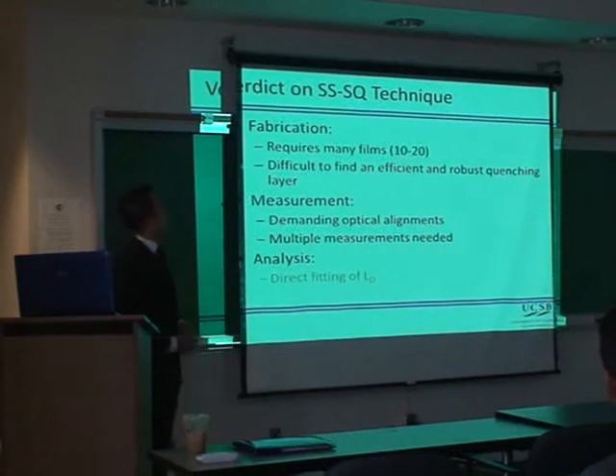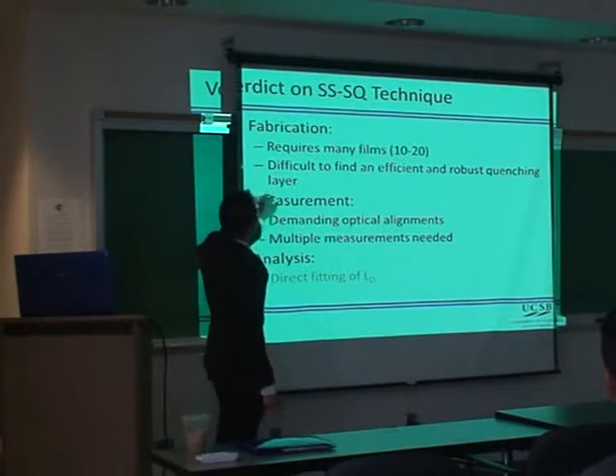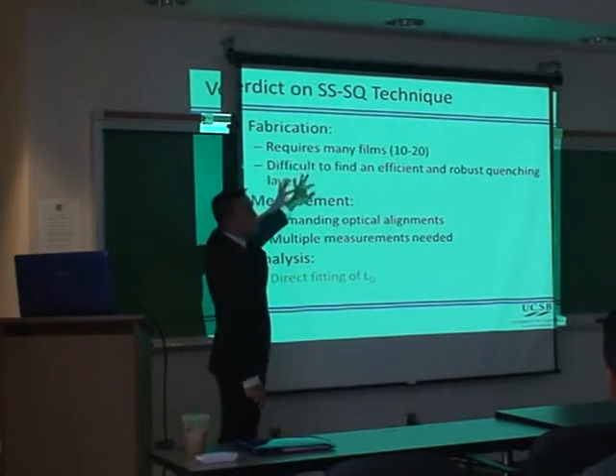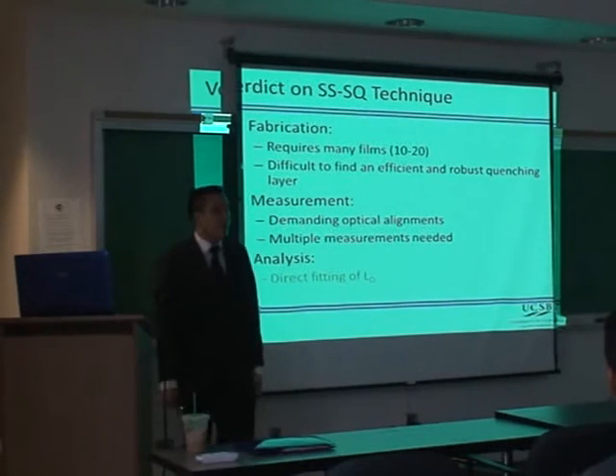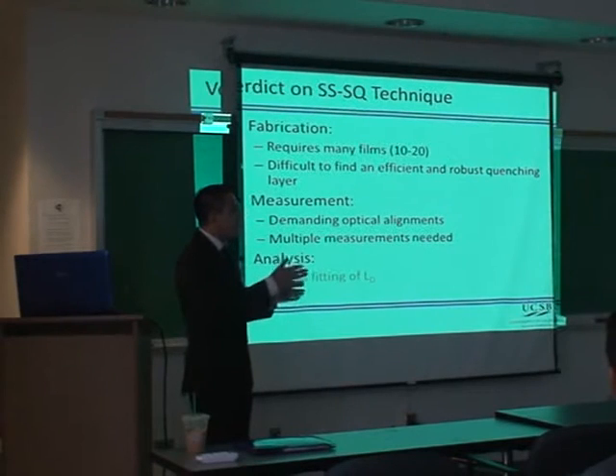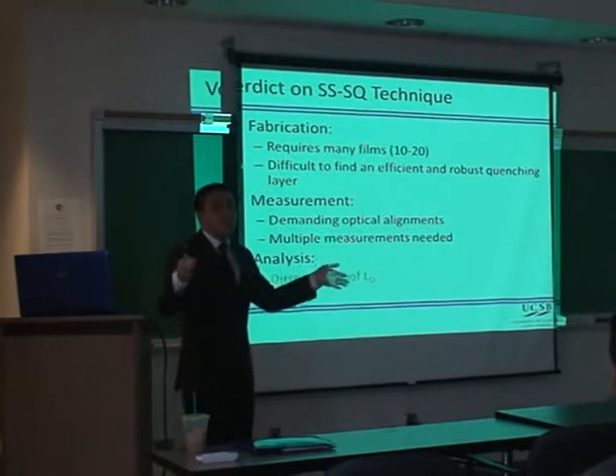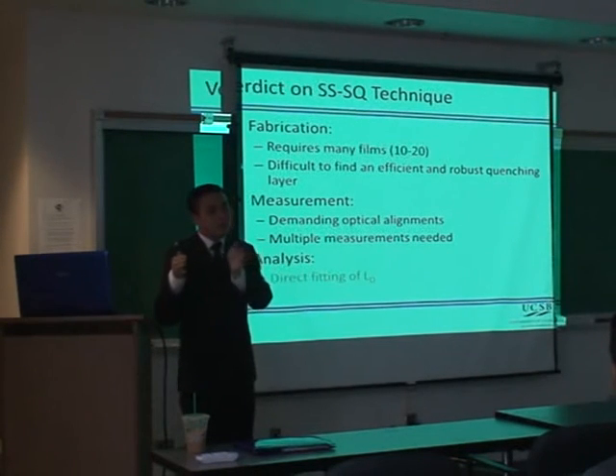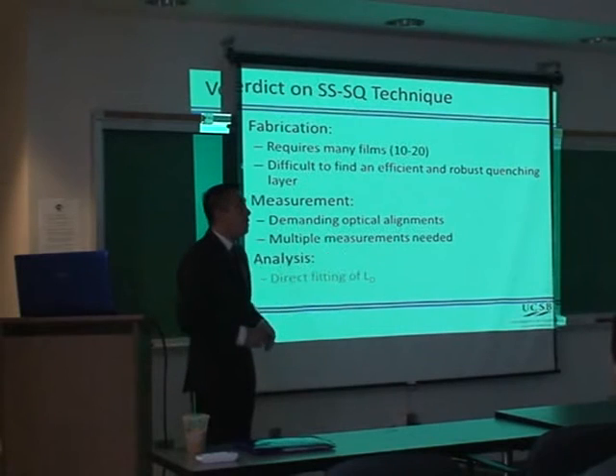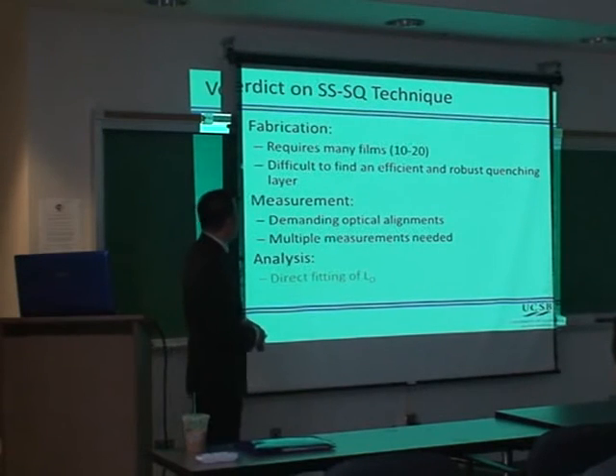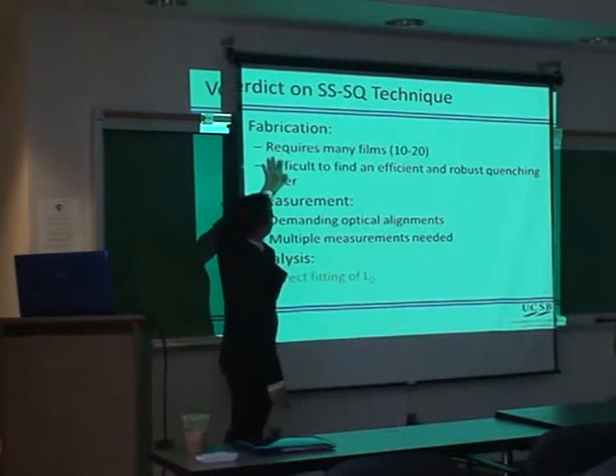So finally, the verdict on this technique. The fabrication requires many films, 10 to 20. I actually reduced the number of films because I evaporated only on half with C60, so I was able to cut it by half. But really, you have to probe a lot of different thicknesses, from 10 nanometers up to above 50 nanometers. So that requires a lot of material, a lot of time.